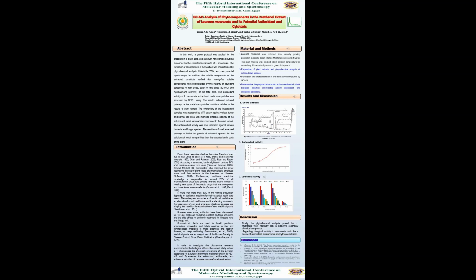According to the results, the extracts of Launaea mucronata exhibited antioxidant activity in a dose-dependent manner, P less than or equal to 0.05, which was comparable with ascorbic acid as a reference standard. Based on the IC50 values, the extract of Launaea mucronata has an antioxidant activity of 31.70 mg per milliliter.